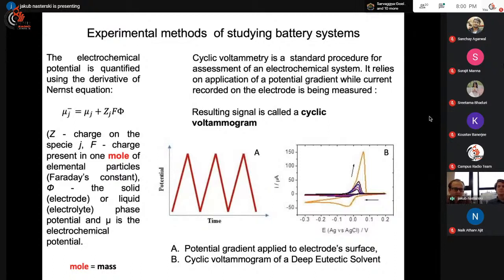So very often, when people want to study electrochemical systems, they use a technique called cyclic voltammetry, and essentially, you can see in figure A, this is an application of a potential gradient. So you apply rising and then decreasing potential to your electrode, and you do that in cycles, and you observe changes in current. So what you apply is in the figure A, and what you see is in the figure B. You see how your current changes over the potential. And depending on what you have in your system, you'll get several different, what they called voltammograms.